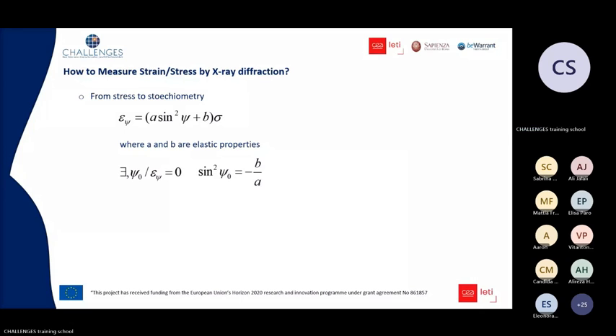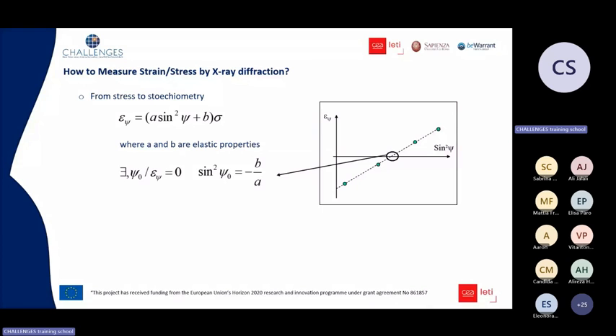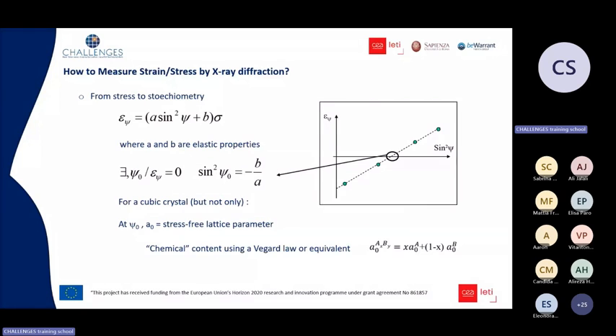So it means that plotting this strain versus sine square psi relationship, this point here gives you the stress-free lattice parameter of the material. And from that, the stress-free lattice parameter can be related to the chemical stoichiometry of the material. And so using Vegard's law, we can extract the composition of the material.